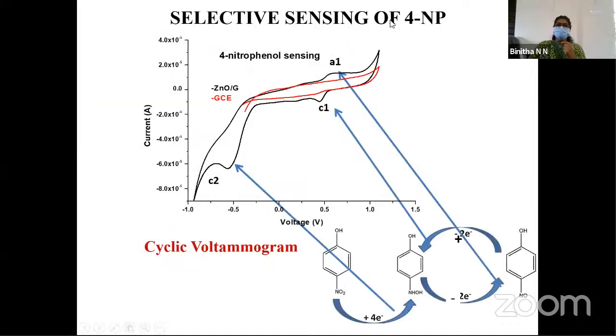Here is the cyclic voltammogram of the selective sensing of 4-nitrophenol. The sensing is performed in the presence of other interfering agents such as glucose, uric acid, ascorbic acid, hydrogen peroxide, etc. And none of the interfering species has produced any peak in the cyclic voltammetry. The peaks correspond only to 4-nitrophenol.